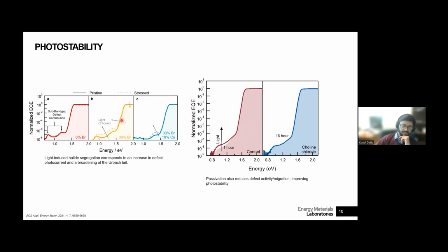But therefore this Urbach tail change that we can see here a little bit doesn't even show up here, but this initial onset of these defects you can see because the solid line is basically much higher than the shaded one. If you contrast that with what we see with the choline chloride sample, the shaded one is the pristine again, and this solid line is after light soaking for 16 hours, they basically overlap. Right? So there is no increase in the defect photocurrent as a result.